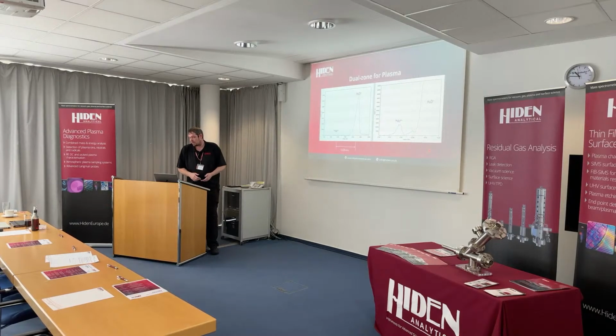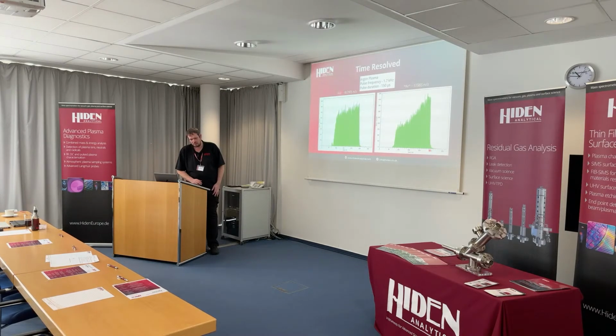So then because it's an EQP, you can also do the ion energy distributions on those if you're expecting them to be different. I chose to do the MCS on it. So there is a difference there. The two ions do behave differently when it's a pulsed plasma, and without that resolving power, you wouldn't be able to separate those. It would be an average of the two.